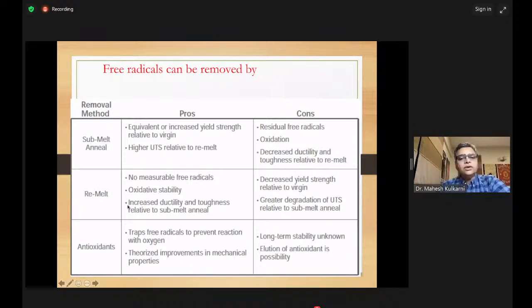What about remelted polythene? The polythene is heated to a very high temperature. The material completely melts away. It takes away all the free radicals. However, it will affect the mechanical properties of the material. So the yield strength will decrease and there is greater degradation of the ultimate tensile strength as compared to the submelted or annealed polythene. So these were annealing, which is submelting 2 or 3 times, and remelt, which is increased heating massively so that the free radicals are taken away.